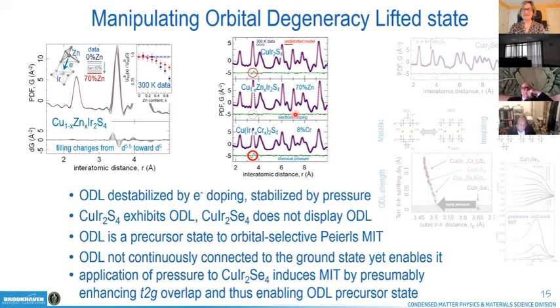Now, what happens to our other sister compound, selenium? What happens is that this actually is cubic at all temperatures, and it's cubic at room temperature as well, and does not display this state. Basically, this state is missing. So cubic model explains local structure perfectly well. If you pay close attention, you basically see that this iridium-iridium peak in selenium variant is actually at a higher distance than in the sulfur variant, meaning that basically the pyrochlore sublattice is expanded, and therefore the orbital overlap is actually reduced.